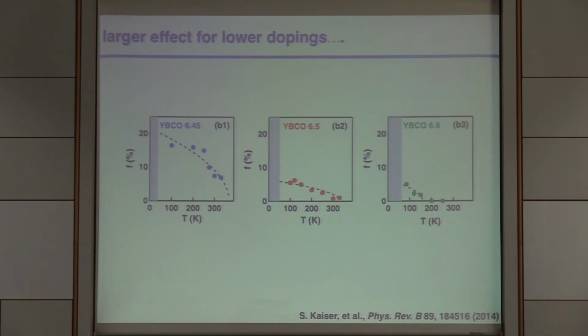Basically, what you have here, you have a threshold below which you don't see anything, and then you have a linearly increasing signal with fluence, and then we don't have enough light to see it saturate in this material. But there's no limit where ultimately it's heating and there's a systematic way in which you can control it. Remember, there's an impulsive excitation, and then there's a relaxation, which we don't understand. This relaxation may involve simply heating or something of that nature, but heating in half a picosecond, usually, you're in a highly non-equilibrium state, so it depends exactly what you mean by heating.